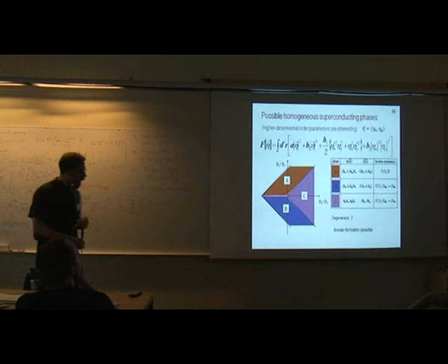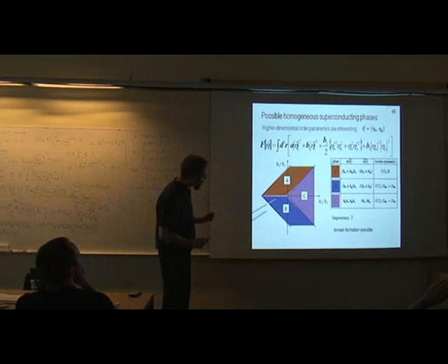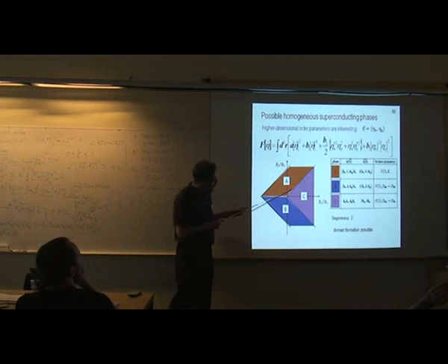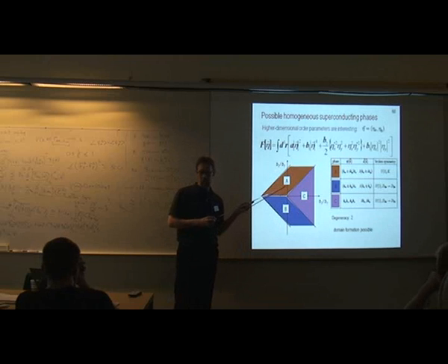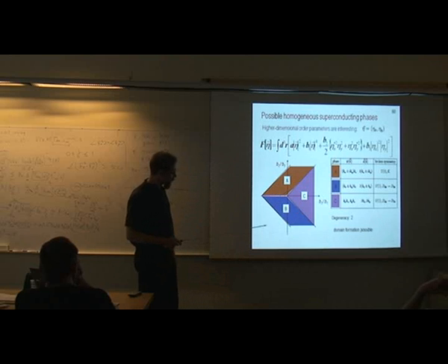All right, so that's important because that lets us show where in the phase diagram the weak coupling theories lie. And that's what I'm showing here. If you look at this condition, that means that all these theories lie along this line. So these are all the weak coupling possibilities you get for this particular order parameter. And you see in which phase they lie. They all lie in the kx plus i ky state. And so you can understand that this is actually a fairly robust result.